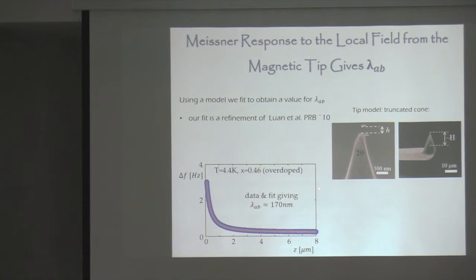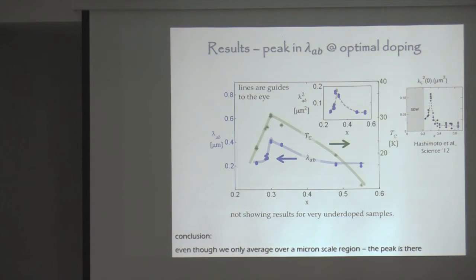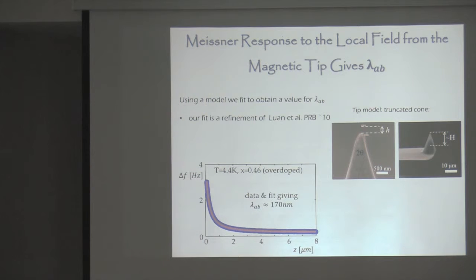So here are SEM images of our tip, which is what we based the model on, and you see that we get very good fits, and there are some tricky things about this fit. So before you use it, talk to me. But from this, for example, in this particular sample, an overdoped sample at this temperature, the absolute value of lambda is 170 nanometers, and it's really cool that you can measure the absolute value of the penetration depth because it's a hard quantity to get. Okay. What kind of error? I would say maybe 10 or 20 nanometers either way.